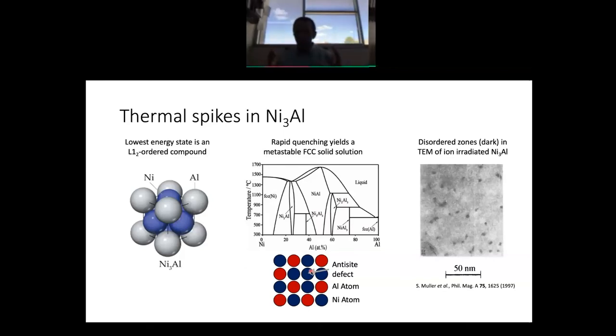So thermal spikes generate these liquid cores. Inside those liquid cores, the nickel and the aluminum atoms take on random locations. When that liquid core resolidifies, the core of the thermal spike is disordered. And this is something that's been seen in experiments. So on the right-hand side here, you see a TEM micrograph of nickel-3 aluminum that was irradiated with ions.